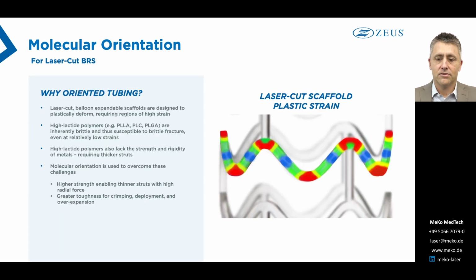But what about a laser cut scaffold? Why would we want to start with an oriented tube? If you consider a typical balloon expandable scaffold design, as we discussed previously, there are regions of high localized strain. So if you take a look at the drawing there, in those red regions, there's a really high strain regions when that stent or scaffold is crimped and deployed, and even when it's implanted in the vessel. So those are regions where the stent has to be very strong and be able to survive that high strain.